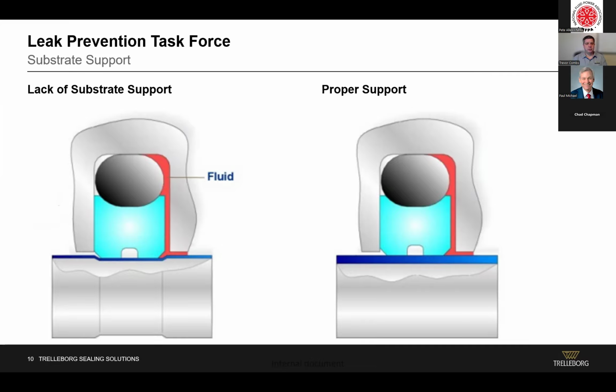Often you'll need to harden, maybe do an induction hardening process on the substrate to make sure that it has the necessary hardness to support the coating. And that coating, if it has the right thickness, will ensure a good dynamic running surface for the seal that doesn't get damaged over time. The coating is typically microns thick, so this picture is not to scale, but just representative of wanting to ensure that you have the right coating and substrate for your system.